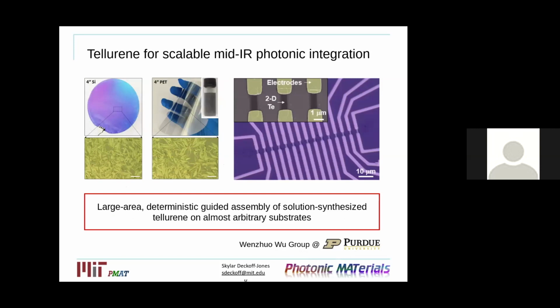However, another very appealing thing of the tellurene is its potential for scalable production or scalable manufacturing. Because it's solution processed, it's quite easy to actually coat a large wafer, and even the type of wafer doesn't matter because you're not worried about epitaxial growth. So here you see that they cover an entire silicon wafer as well as a PET wafer. And you do see that there's sort of this random distribution of flakes. They do have a lot of different thicknesses and orientations, but Professor Wenzhuo Wu's group is now making great progress in being able to control the orientation as well as the thickness. So having a small standard deviation in the thicknesses of the flakes, as well as having them uniformly oriented along preferential directions. And additionally, you can also etch the tellurium as needed for, in this case, they're looking at, again, transistors, from its usual sort of trapezoidal shape.